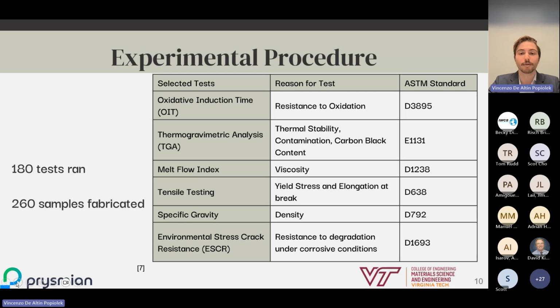We ran melt flow indexing to check for viscosity, tensile testing for yield stress and elongation at break, specific gravity for density, and environmental stress crack resistance, or ESCR, for resistance to degradation under corrosive conditions. For those of you not familiar with ESCR, what we do is we mold a plaque out of the polymer. From this, we then punch out tabs. These tabs are then nicked with a nicking jig to induce a stress concentration. These are then bent along the stress concentration and added to a metal grid, which keeps them in that stressed position. This metal grid is then added to our corrosive conditions, which in our case was a slightly basic solution. The corresponding ASTM standards are listed on the right.